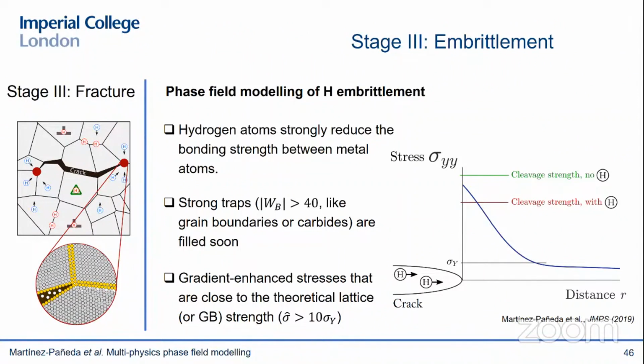But the key thing is that if you resolve the stresses ahead of the crack tip over the critical distance, what you see is that in the absence of hydrogen, your stresses are not high enough, so you don't reach that cleavage strength or grain boundary strength. But the moment you bring hydrogen into the picture, you get this 30 to 40% reduction in cleavage strength or in grain boundary strength.